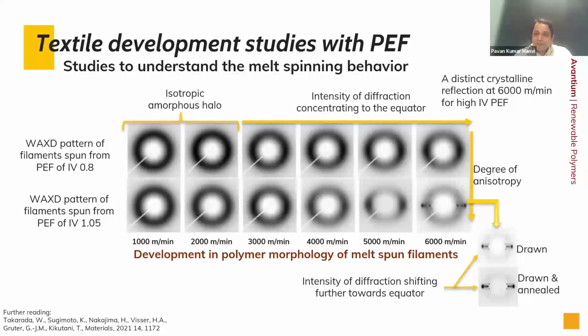Here you can see how the WAXD pattern is changing as we increase the speeds. At the lower speeds, 1000 and 2000 meters per minute, there is mainly the amorphous halo. But if we increase the speed, then at the lower IV, here 0.8, the intensity slightly moves towards the equators.